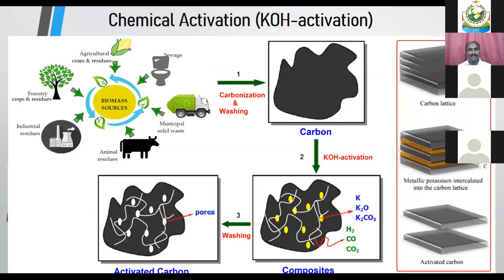And chemical activation. So what do we mean by chemical activation? How is the porous carbon activated and how can we get the porous carbon? So these are the biomass sources. This biomass resource is collected, then carbonization and washing is the first step. The second step is the KOH activation. KOH is the chemical, so it is a chemical activation. And the third step is the washing. Initially we have carbonization, we get the carbon. This carbon has no porosity, so we need to create the porosity.